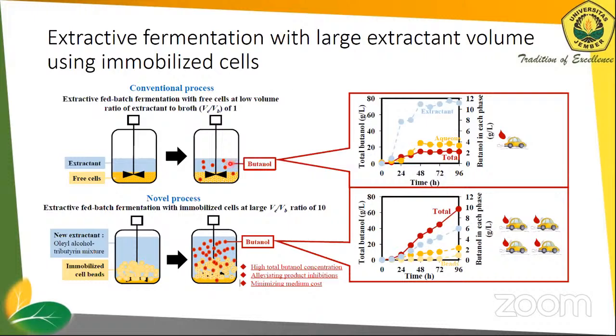We also use immobilized cells to protect the cells inside from the toxic environment containing butanol and also acetone and ethanol. Here, this is the conventional process with normal extraction, with low ratio of extractant to medium. And this is the extractive fed-batch fermentation with large extractant volume and immobilized cell. Here we can see that the total butanol produced is 4 times higher. So we try to use this for the biobutanol production.